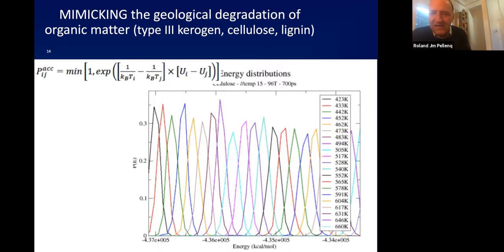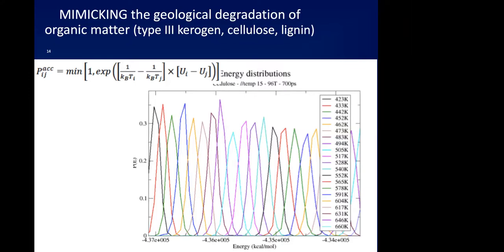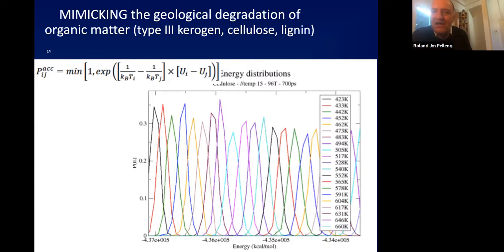If you look at the classical physics of things, when a liquid, for instance, at a given temperature, the energy distributes as a Gaussian distribution over all possible states of the liquid. If you now do the simulation at a temperature a bit higher than that given temperature, you have another Gaussian distribution of energies. But because temperatures are not too far away, those configurations actually overlap. That's the key thing, because in the overlapping region, configurations that exist at a given temperature can also exist at a temperature a bit higher or a bit lower, depending on which side of the histogram you're on.